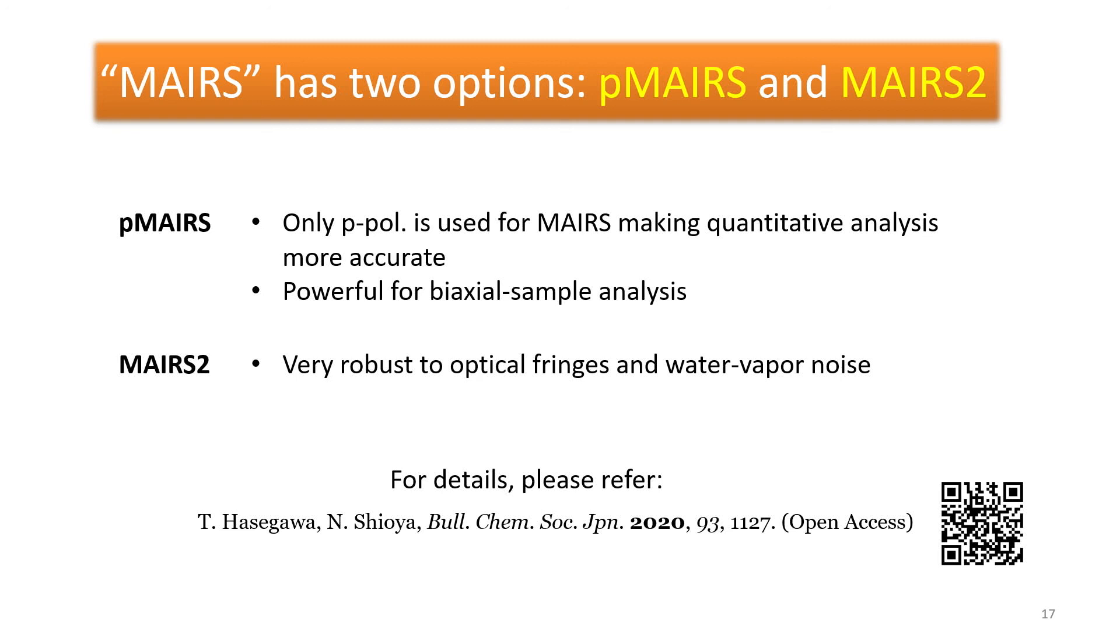p-MAIRS employs the p-polarization only, which makes FTIR free from the matter of polarization dependencies. In fact, a very accurate analysis is possible using this technique. In addition, if you want to analyze a biaxial sample, p-MAIRS is recommended.